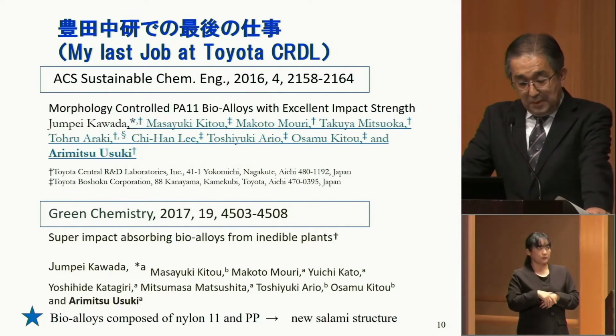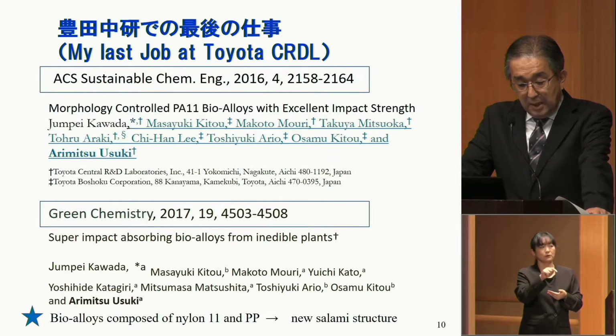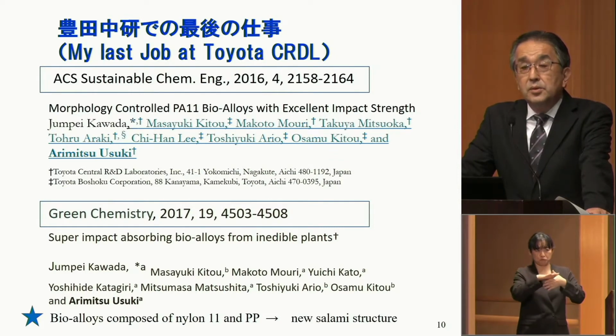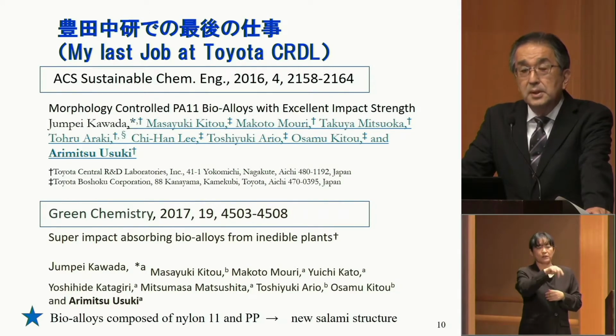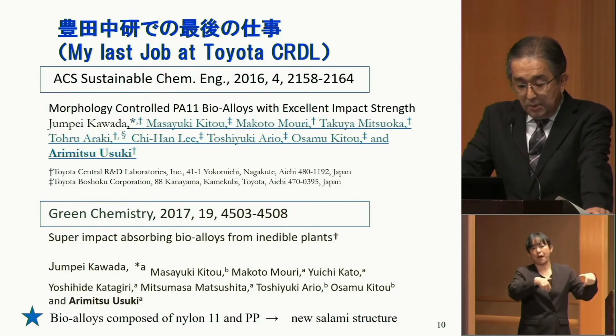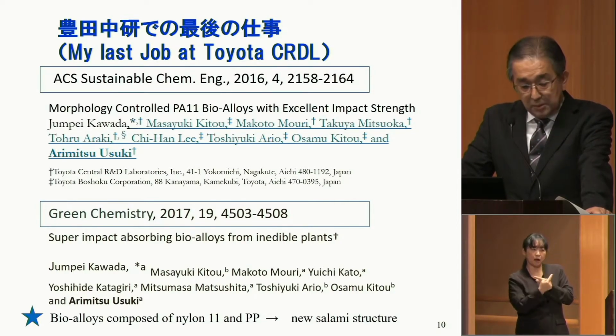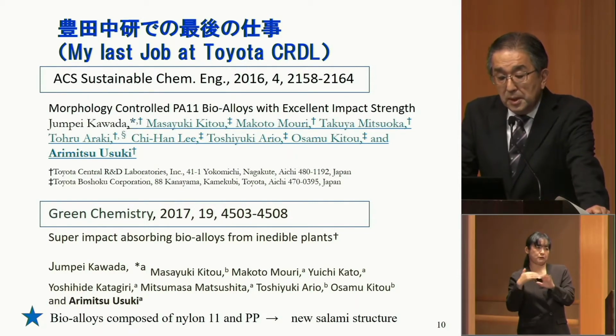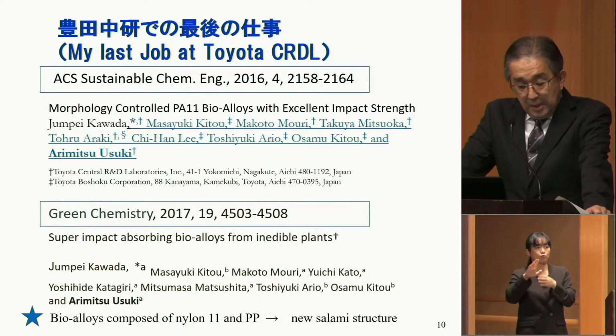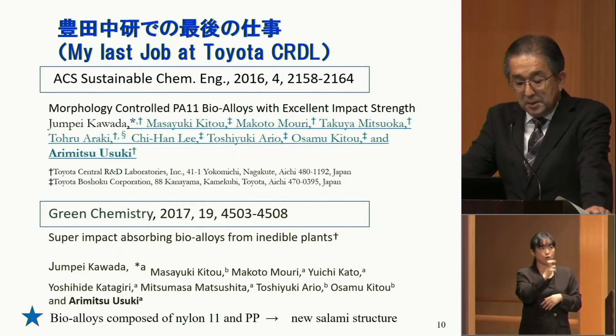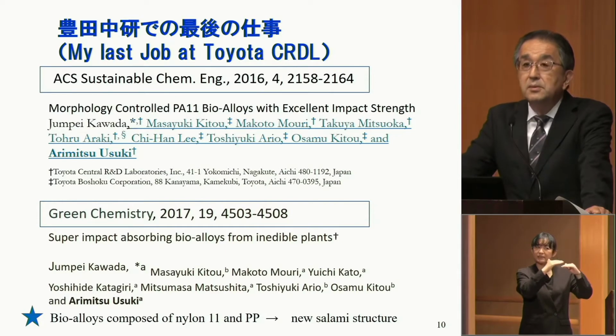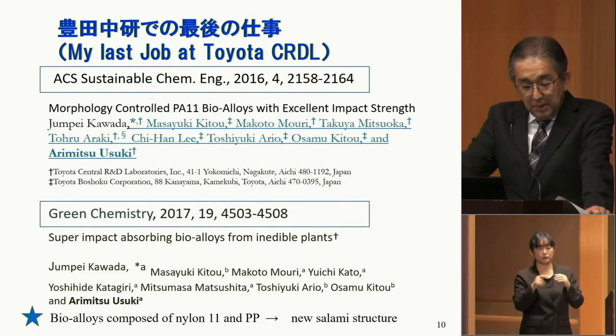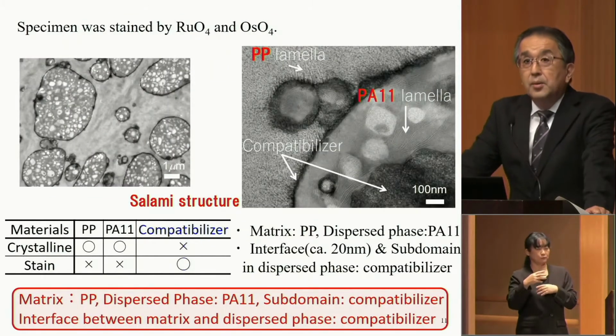And now let me touch upon my last job. There are these two papers. It was the creation of bio-derived nylon 11 and polypropylene, PP, alloys, which are also used for vehicles such as bumpers. We mix them into an alloy, which becomes a very good material again. We published papers in 2016 and 2017. The nylon 11 was dispersed like islands in polypropylene, and a new salami structure was found. These were summarized in these two papers.